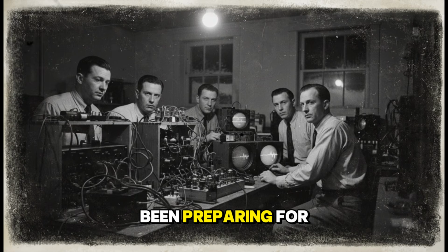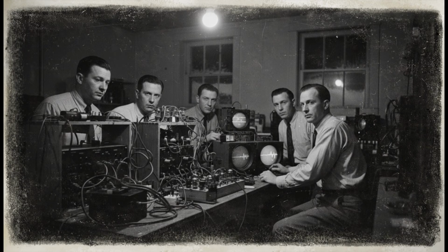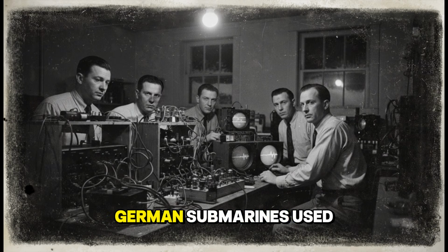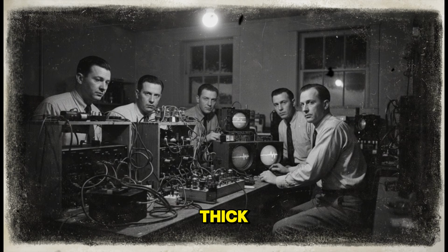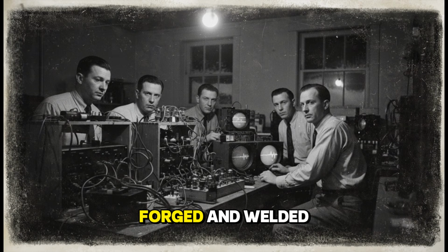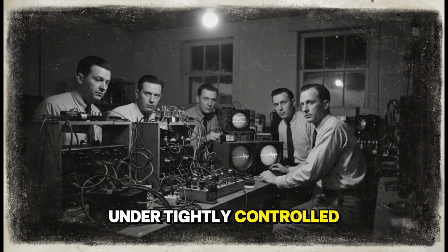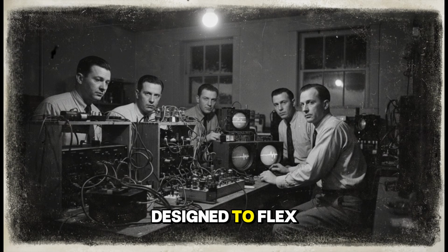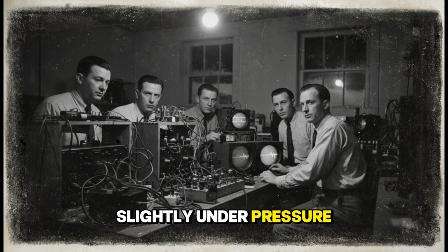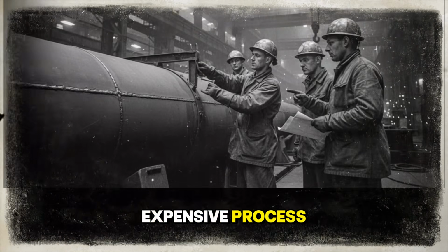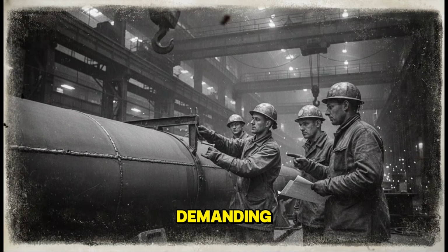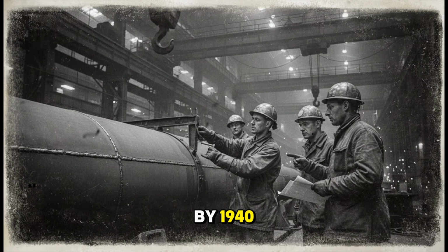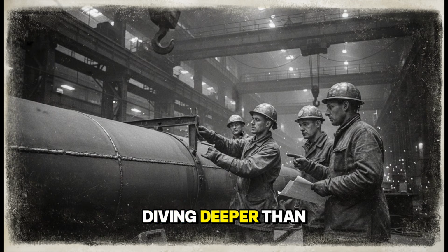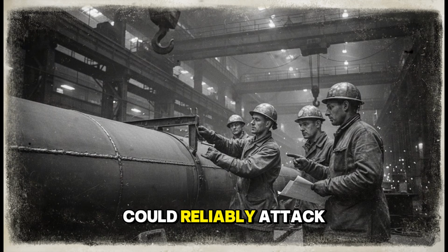German industry had been preparing for this long before the war began. Krupp and other firms had refined pressure hull metallurgy through years of experimentation. German submarines used thick, high-tensile steel cylinders, forged and welded under tightly controlled conditions. The hulls were designed to flex slightly under pressure rather than crack. It was an expensive process, slow and technically demanding, but it worked. By 1940, U-boats were diving deeper than many Allied escorts could reliably attack.